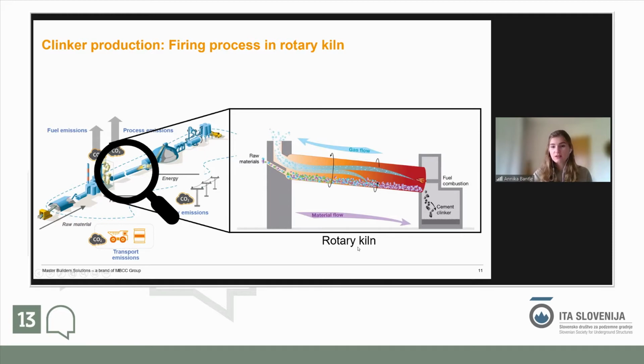So you have the rotary kiln here in a little bit more detail. You have the raw material flow from left to right, and in the end you end up with cement clinker. You have the fuel combustion to get the heat into the system and to have the decarbonation process, and the gas flow is originating here, you can see it, and you end up with CO2 emissions per ton of cement clinker of up to 900 kg.